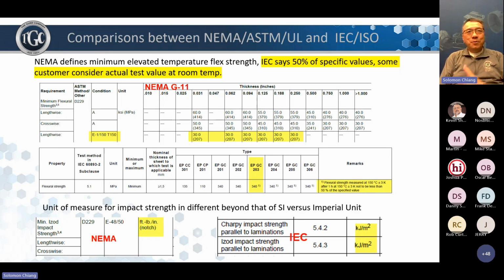Okay, but then IEC put it in the remarks, and then sometimes people can construe that, instead of it being half of the requirement at room temperature, it should be half of the actual test value at room temperature. So material that outperforms at room temperature would end up having a higher bar to meet at elevated temperature. For example, IEC EPGC 203 is 340 MPa at room temperature, so that means 170 at elevated temperature. But if your material tests out at 600 MPa at room temperature, some people may argue that it has to be at least 300 MPa at elevated temperature. That is not the intent of IEC.